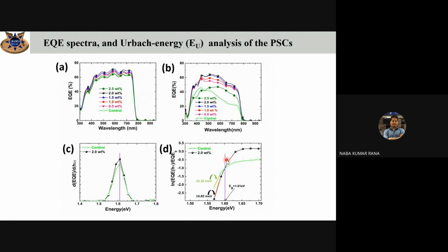And this is the external quantum efficiency spectra of the small area and the large area devices. The spectra change slightly here due to the decrease of uniformity in the large area devices. Now we calculate the band gap from the quantum efficiency spectra, which I already saw from the UV spectra. Both are the same. That's why the bandgap does not change with the introduction of Al2O3, but it enhances the carrier extraction from the respective transport layer. This passivation effect is clearly found from this graph.